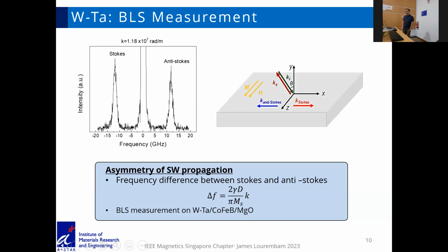Then we look at the DMI, which is measured by Brillouin light scattering. These were done by Dr. Sylvia from the University of Perugia. Basically, the Stokes and anti-Stokes peaks correspond to creation and annihilation of magnons, and the difference in the counter-propagating waves, given by delta F, is proportional to D. So one could do this experiment to get the difference delta F and determine the DMI in the system.